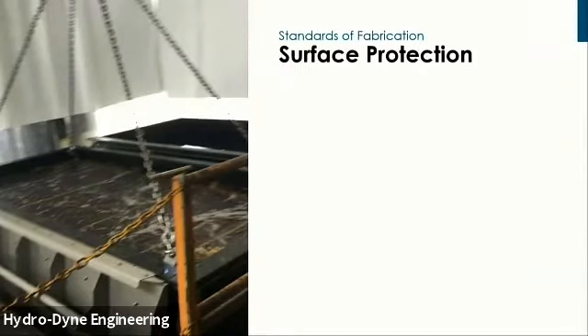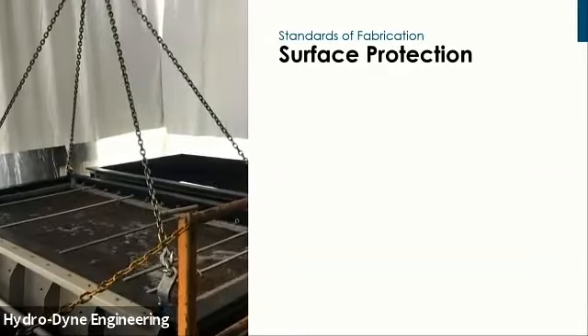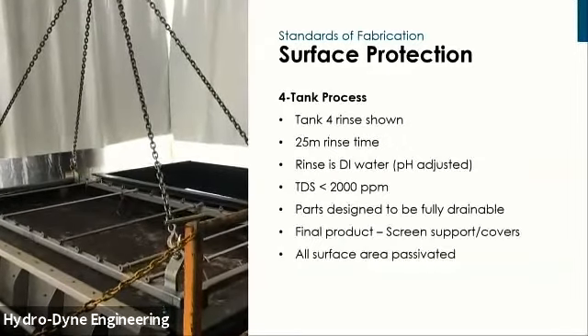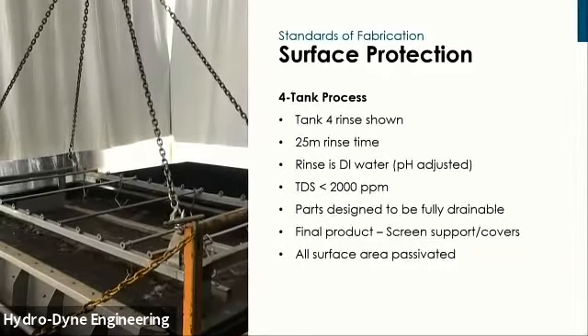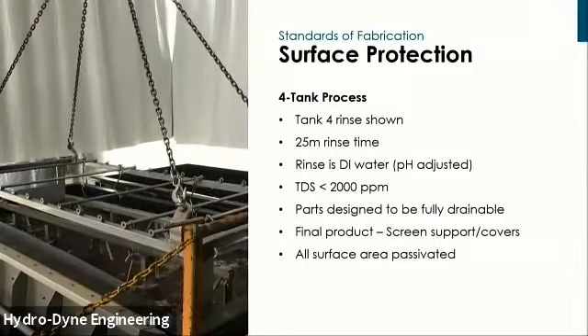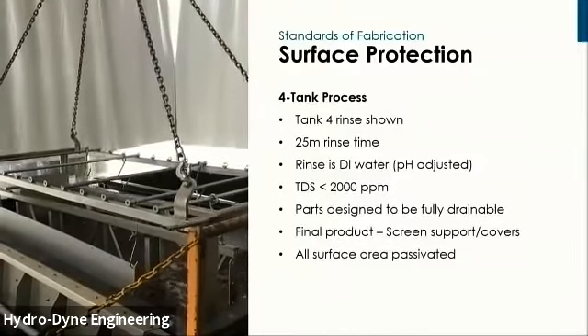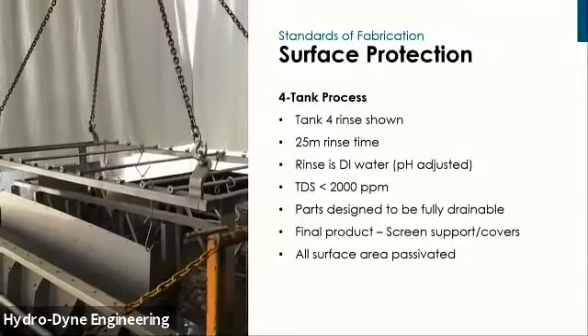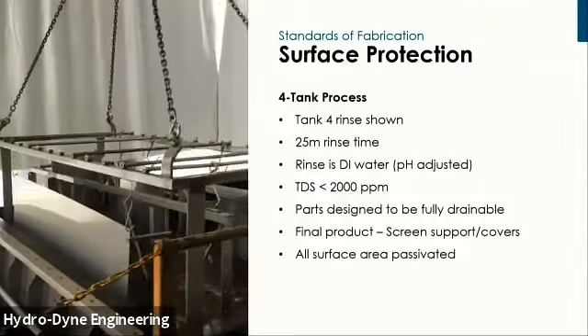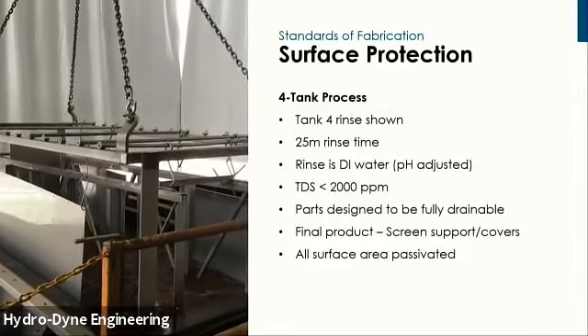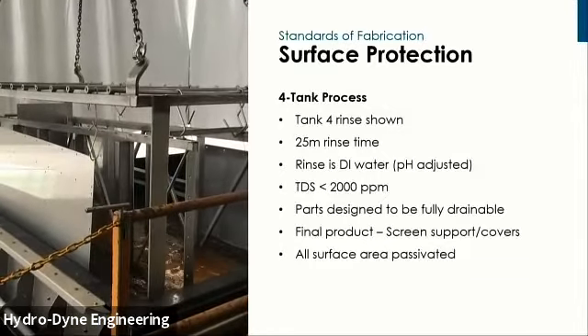Let's show that a little bit. So in this case, we have our tank 4 rinse. And this is equipment coming out of our rinse tank. It's generally a 25-minute rinse time, and we rinse with DI water. You can see that all the parts need to be fully drainable, so we can't have liquid hanging up on any part of the screen. And in here, we've got the final product as screen support and covers that are coming out of our rinse tank. So the entire surface area is cleaned and passivated, and ultimately corrosion protected.